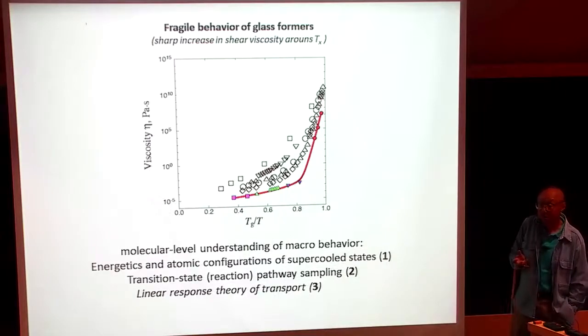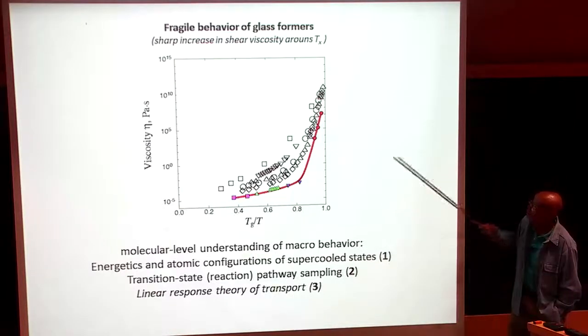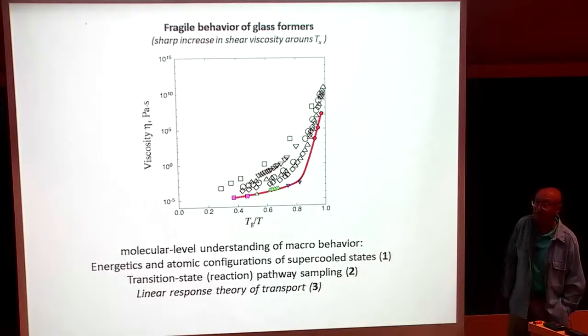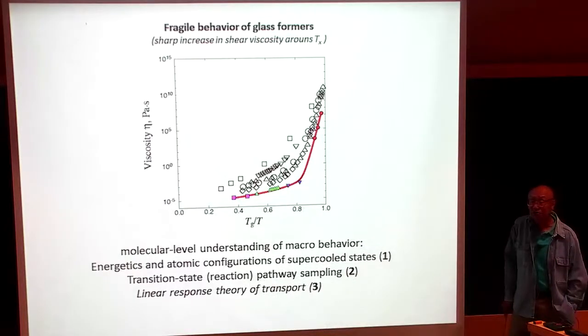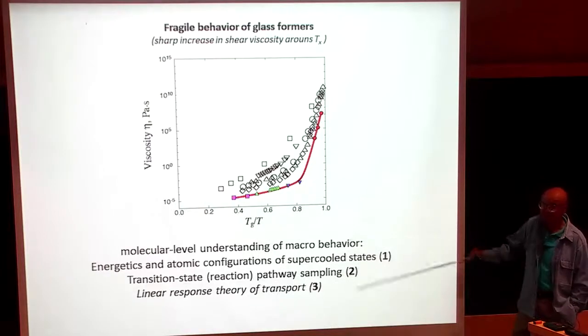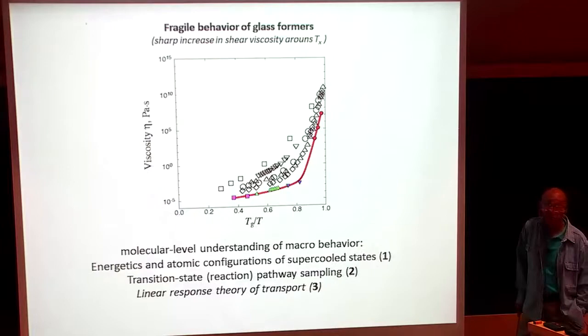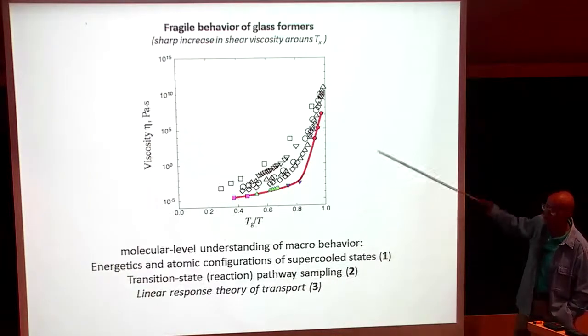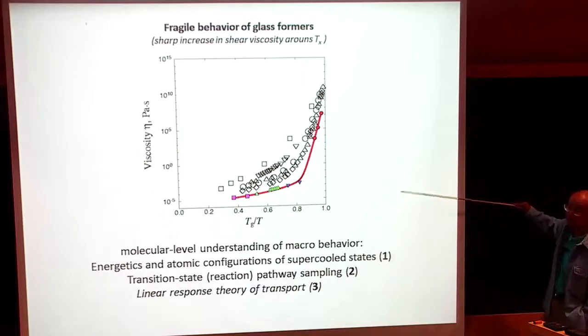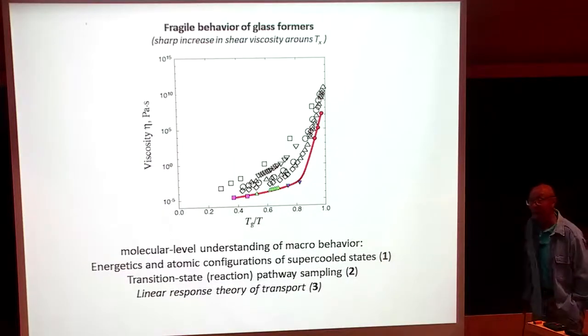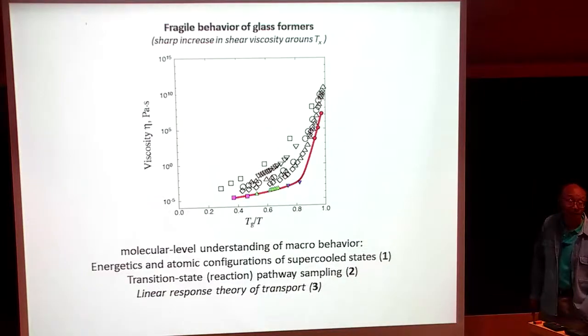Now let me also say right now that this Tg is purely a convention within the community. Other people who only look at structure don't define Tg according to the viscosity. They use Tg according to whether or not the radial distribution function has a split second peak. So if you cool the liquid down, the second nearest neighborhood peak of the radial distribution function all of a sudden splits. So there are other measures, indications of some kind of transition. Not really a transition in the phase transition sense, but this glass transition. There are other ways.